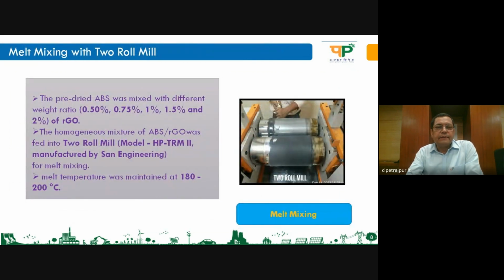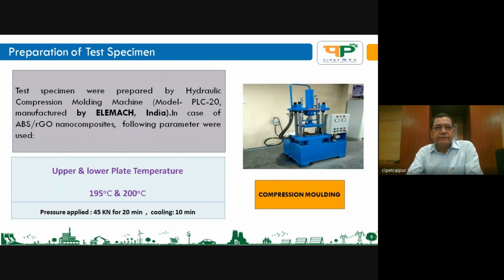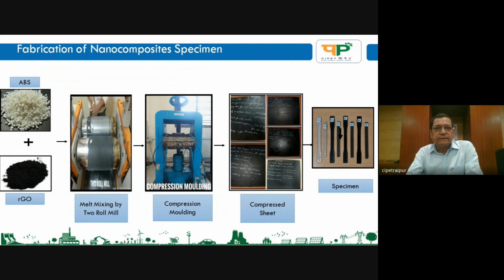First we have done melt mixing with the help of a two-roll mill, and we have taken different loadings of 0.5%, 0.75%, 1%, 1.5%, and 2% of RGO. With this, we have made different specimens, and the temperature was maintained at 180 to 200 degrees, which is suitable for ABS. And the machine which we have used is a compression molding machine. We will not go into detail. This is the fabrication of the nanocomposite specimen.